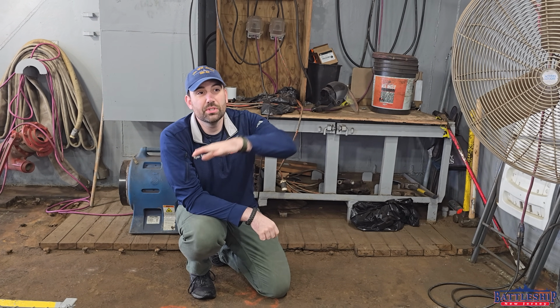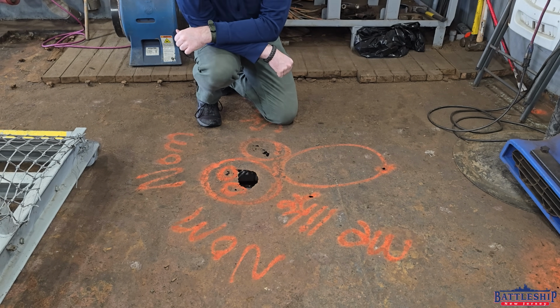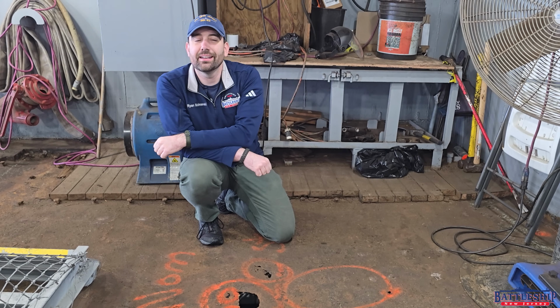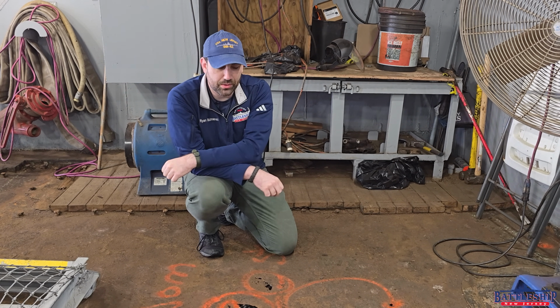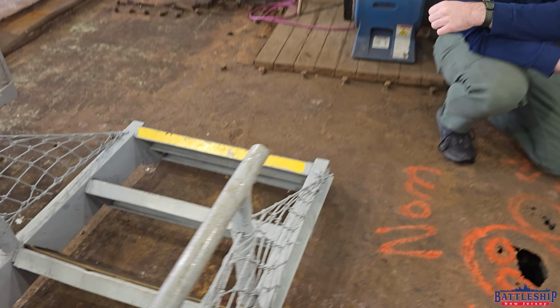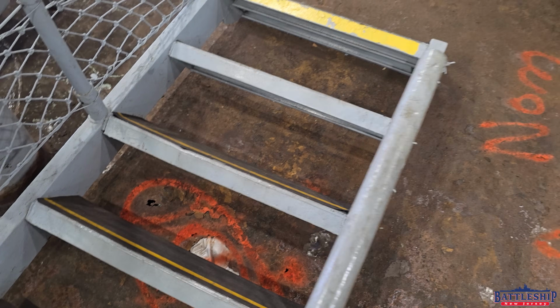And when we had the ship in dry dock, she was sitting perfectly level. And we found at that time that water sat on this deck under the overhang and leaked into some of the staterooms down below that we hadn't previously believed were a problem. And so we had to prioritize coming up here to this space to see where the little pinhole was that was leaking. Well, it ended up not being a pinhole and it ended up not being one hole. We're showing you one of the worst areas, but it is far from the only one up here.